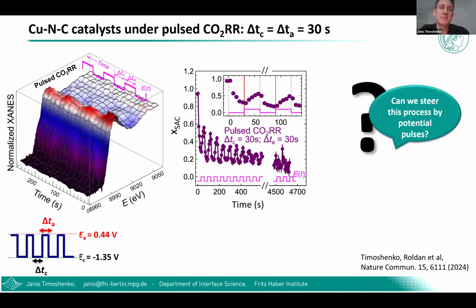So the idea here again was similar to what we did before with these copper cubes and larger copper catalyst particles. So instead of applying static negative potential, we now want to apply pulsed reaction protocols, where we interrupt the negative potential with short pulses of anodic potential and try to see how it can affect the structure of the catalyst. And again, just by looking with the naked eye at your spectra, you can see very nicely that X-ray absorption spectra follow the changes in the applied potential, and we see periodic switching between the cationic state and metallic state of this catalyst, which in this case takes place on a scale of 30 seconds.